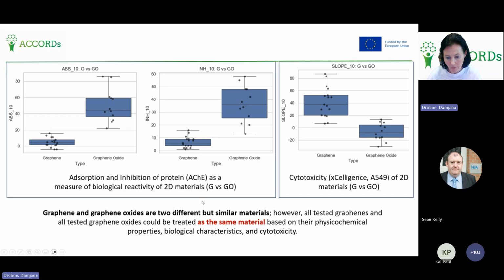What we see here, we have more materials. Here we have materials from the main study, not just from the preliminary. And based on the characteristics we had and on the absorption strength or potential or intensity, we can very nicely group graphene and graphene oxide as the same group. So all graphenes, although they have very different characteristics, and all graphene oxides, they have the same type of behavior.